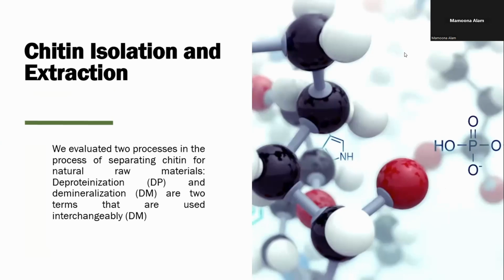We evaluated two processes. There are two challenges in order to obtain or isolate chitin from raw crab shell: one is deproteinization and the other is demineralization. We have to remove the proteins and the minerals in order to achieve the chitin or chitosan. Basically, I treated the crab shells with sodium hydroxide at different concentrations on a hot plate until the color disappears, which shows that the protein has gone. After that, I filtered the product and then retreated it with different concentrations of HCl until I got a clear white powder.